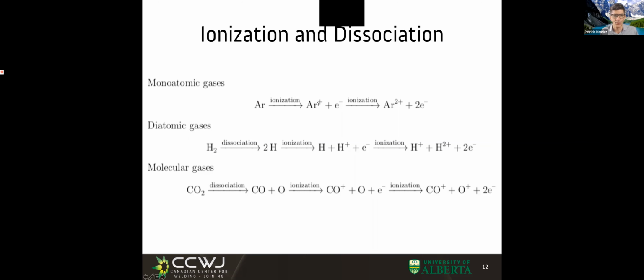Those are the gases we put in, but at the temperature of the arc, they dissociate, right? So the argon can lose an electron, and all of a sudden we have a positive, huge argon ion and a very small and fast negative electron going around. And if we are very, very hot, this argon ion might lose a second electron, right? Sometimes you get to see in argon that if you are too hot, you start to see this second ionization. It's not that common. Diatomic gases like hydrogen,